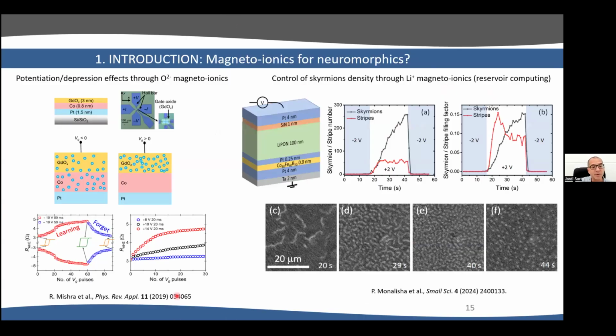Then, interestingly, in 2019, there was this work by the group of Mishra and collaborators in which they showed that this magneto-ionic effect can be used to mimic synaptic functionalities. They studied what happened in cobalt with gadolinium oxide when you apply voltage, negative or positive, and they saw that oxygen ions can move from gadolinium oxide to cobalt or vice versa, depending on the voltage polarity. These are indicated by these blue spheres here. This motion of oxygen between the two layers caused either an increase or a decrease of the Hall resistance, the anomalous Hall effect. And this mimics the learning and forgetting processes in the brain.